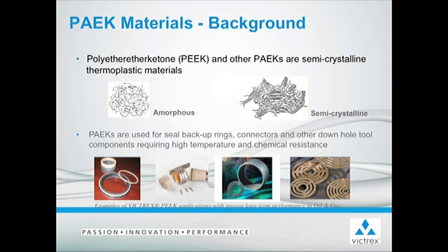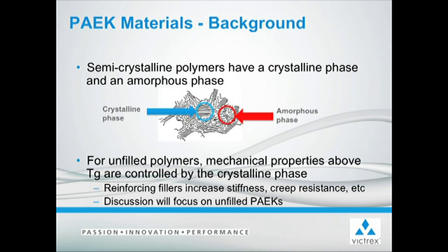Those crystalline regions act as reinforcing structures within the amorphous matrix and give the polymer some additional properties beyond what you'd see with amorphous materials, including mechanical properties like creep and fatigue, and chemical resistance. Again, semi-crystalline polymers are composed of an amorphous matrix with crystalline structures that act as reinforcements within the matrix. For unfilled polymers, the mechanical properties above the glass transition temperature are controlled by the crystalline phase. For amorphous materials, there's no crystalline phase, so there is very little in terms of mechanical properties above the glass transition.